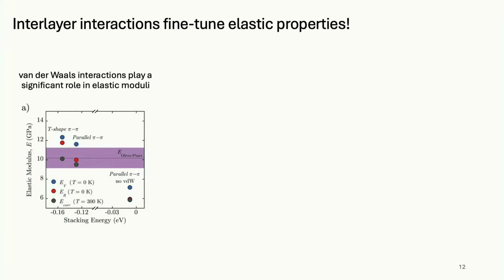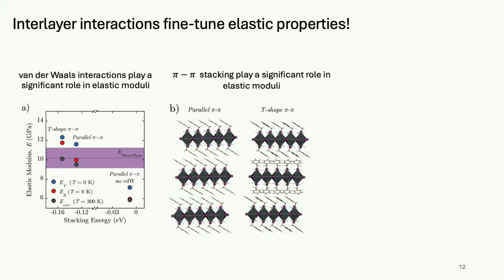Okay. So the final thing that actually helped us quantitatively model the elasticity is to re-examine the molecular layers. Remember our friends, the molecular layers. There's a benzene ring here, but it's tilted, so you're only looking at it side on. Here, you can see the molecule a little bit better over here. So this was the way we modeled it. This is actually a smaller unit cell, so it's sort of the first thing you would do, where you have the molecule stacked up like this. We'll call this parallel pi-pi stacking.